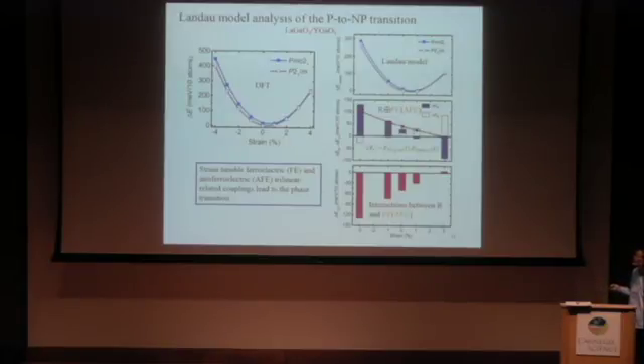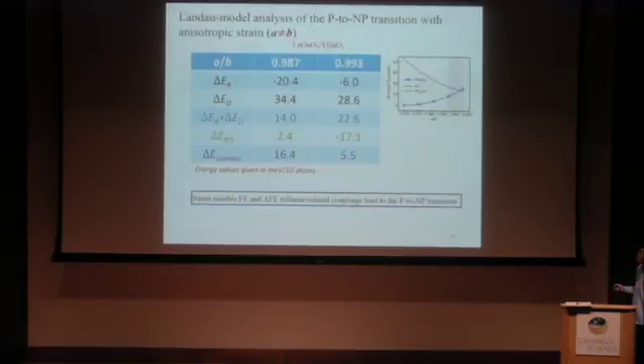Responsible for compensating the energy difference between the first two parts in the two phases, and also leading to the correct phase diagram obtained from the two figures. And this mechanism is also applied to the phase transition under the anisotropic strain.